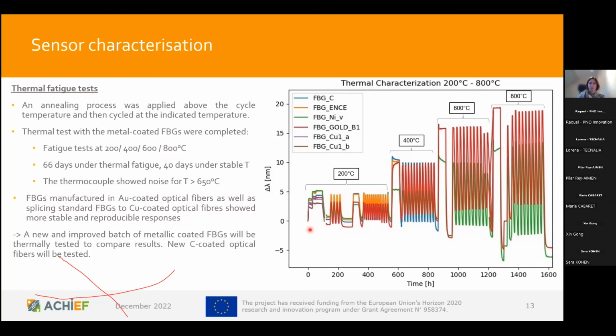In a first experiment, we were curious about the performance of these sensors after the metal coating. And what looks here at first glance maybe a bit unspectacular is really an achievement of its own, because we have here a sandwich structure of a glass fiber, a carbon coating, and a metal coating, with no adhesion layers in between, but the cycling does not destroy or delaminate any of the coated layers, and the fiber optic sensors still work nicely even when we cycle them over nearly 3 orders of magnitude. So we were very happy to see that the sensors were still working, and we now need to confirm that this is reproducible and also define which exact metal coating and which fibers to connect these sensors with then show the best and most stable results.